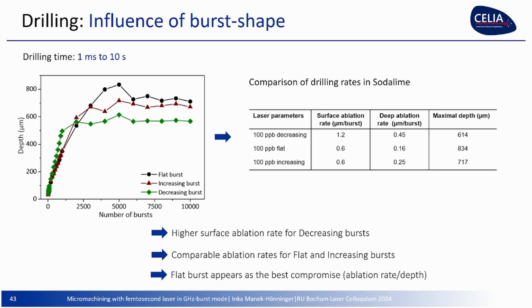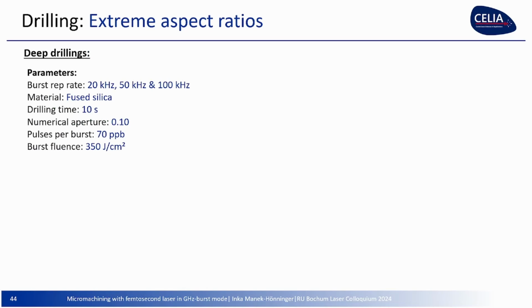So if we compare it, here we can have a higher surface ablation, so we go further, faster for decreasing burst, and we have comparable ablation rates for the flat and increasing. Let's go towards extremely high aspect ratios. How far can we go? Then we have to optimize.